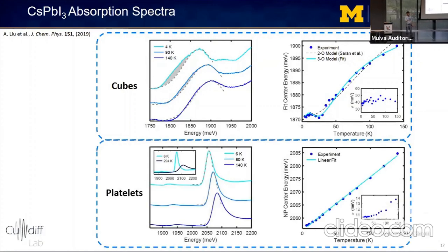If we look at comparable absorption spectra of the perovskite nanoplatelets, we immediately see that the absorption line widths are much narrower. And in fact, the energy windows of these two plots are the same, so you can directly compare the peaks by eye. And if we look at the fitted center energies as a function of temperature, we find that the center energies vary linearly with temperature, indicating that exciton phonon coupling is primarily with acoustic phonon modes.